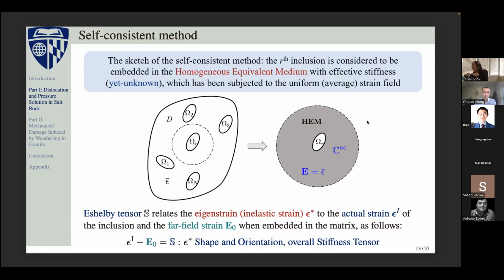And here, if we look at the bottom equation, that is a fundamental equation in this mean field homogenization relation, and it tells us how to link the local behavior to the global behavior. On the left-hand side of this equation, we can see how the epsilon, which is the strain in each inclusion, the local strain, deviates from the capital E naught, which is the average strain of this RVE. That deviation is linked by a linear relationship to the eigenstrain.